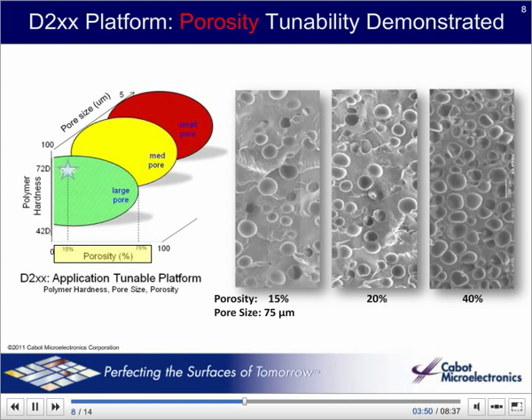In CMC's process for making D200 pads, we can control the size and concentration and hardness of the pores. Here we see what 15, 20, and 40% porosity looks like in the foam.